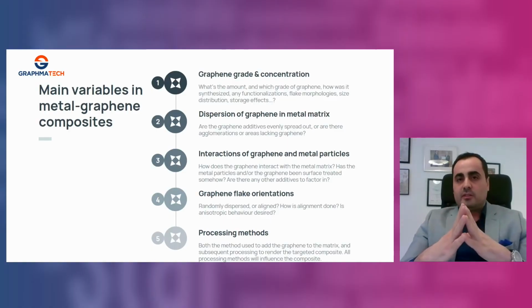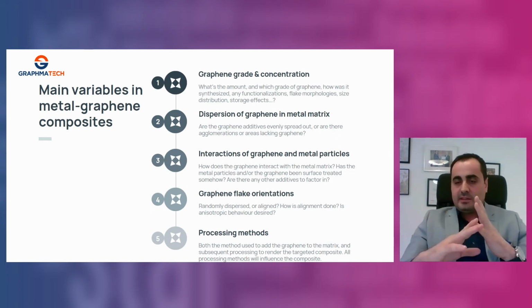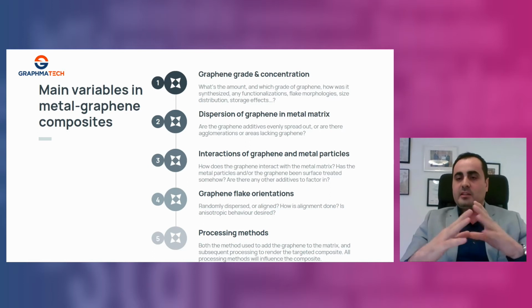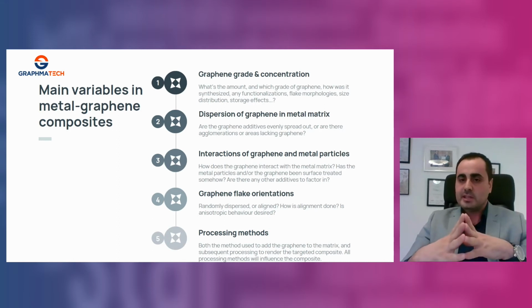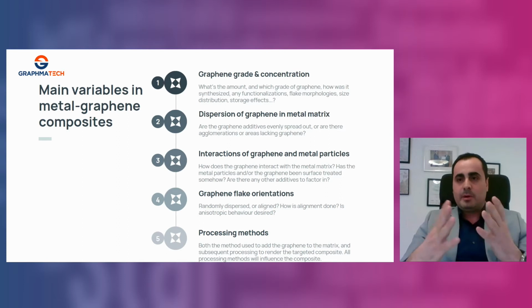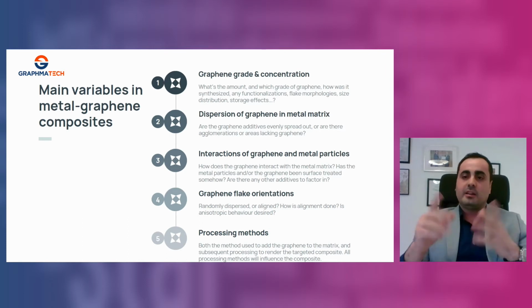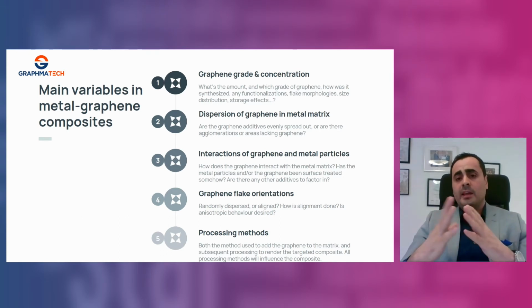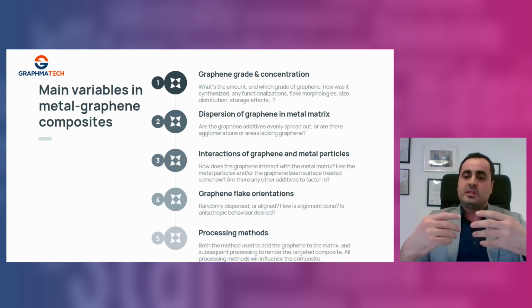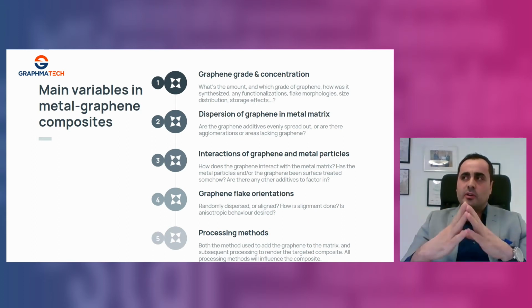Here we have different things to take into account when we are designing or making this material. For example, what graphene grade, as I just presented. How is the dispersion of this additive inside the matrix? How is the interaction between graphene and the metal matrix? How is the orientation of the flakes? Because in some applications, the orientation is extremely important. For example, heat dissipation. Graphene is really great in plane, for example, and if you have few layers, it's less great in thermal heat dissipation. And then, of course, the processing method. How will this composite later be processed by the industry? Are we going to reinvent the implementation method, or are we using the existing processing technology the industry already invested in?